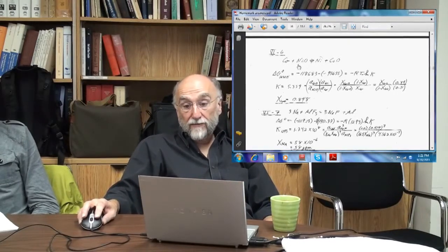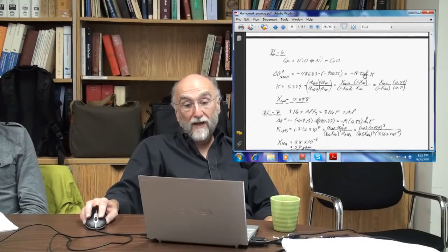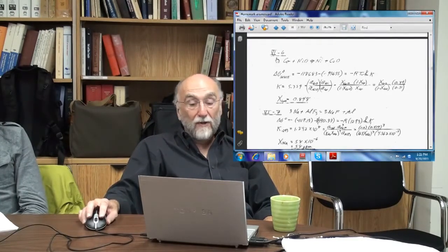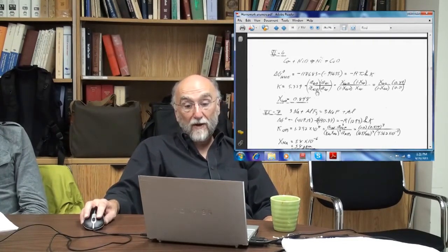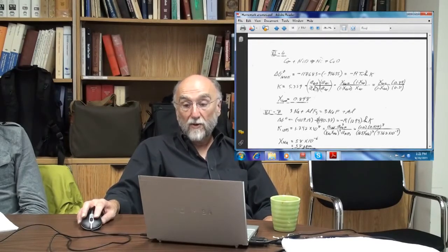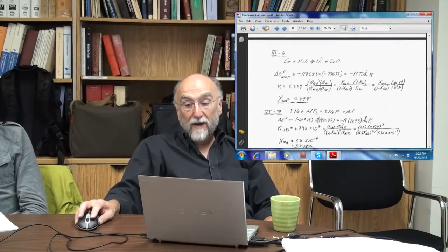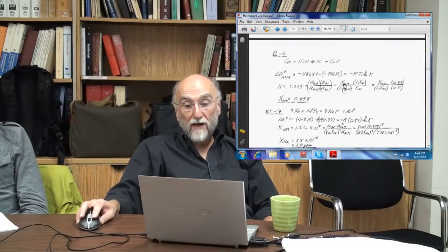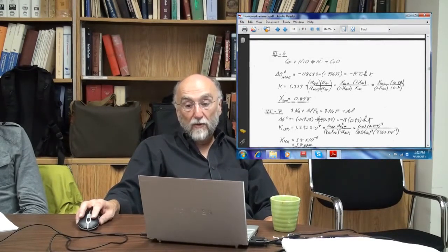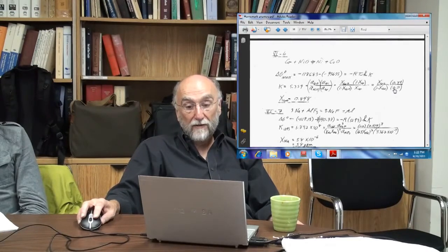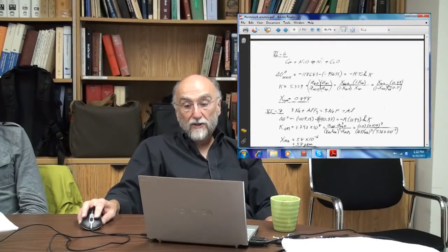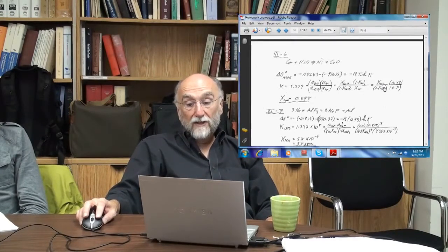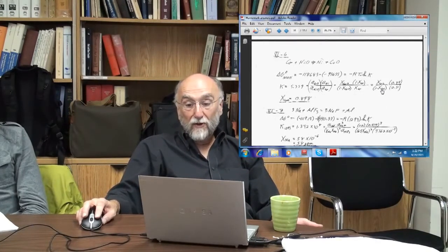Okay, it's actually reasonably close to 0. The K is just slightly greater than 1, so it goes slightly to the left. But at equilibrium, you're going to have a reasonable amount of cobalt and nickel in both phases. So at equilibrium, we're assuming an ideal solution in the metal phase, so the activities are equal to the mole fractions. This is the ratio of the mole fractions, hence the activities, in the metal phase. And this is the ratio of the mole fractions in the oxide phase, the mole fraction of nickel oxide being 1 minus the mole fraction of cobalt oxide.